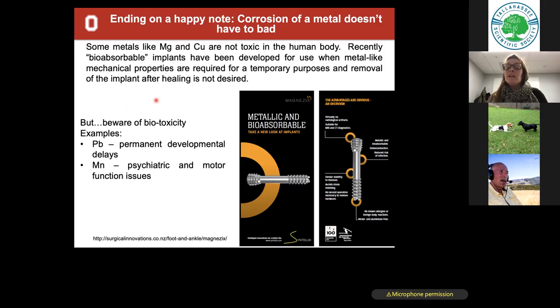Magnesium, in fact, is being utilized in modern times as a bioabsorbable implant. There are many reasons why you get a metal implant and you don't want it to stay, right? If your hip's replaced, you want that to stay. But if you broke a bone and you just need to mend it until that bone can heal itself, you can put a screw in and actually implant a magnesium alloy that will corrode in a very specific amount of time. So you can tailor the corrosion properties based on what you put in it and how you process that magnesium alloy. And when you do that, you can cause it to corrode in a timeline in which you believe the bone will have healed. So these are examples of screws that are magnesium based that serve a temporary purpose. And then it corrodes and you basically just urinate it out, right? It doesn't corrode in a day, but over time it will corrode and your body will dispose of it properly with no harm to you, which is great because you don't have to live with a screw in your body for no good reason for the rest of your life.